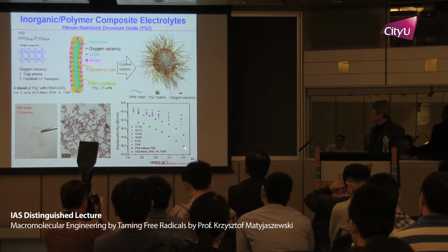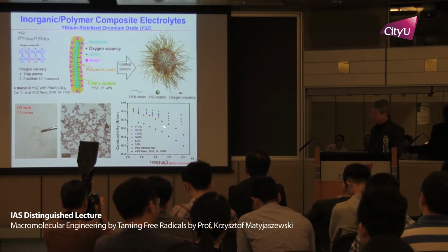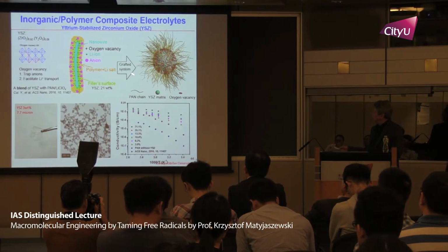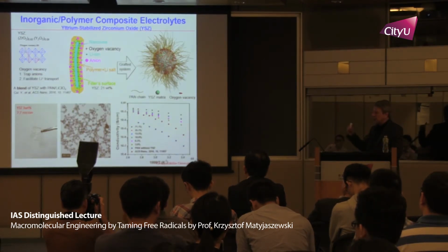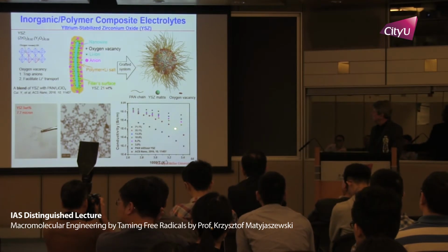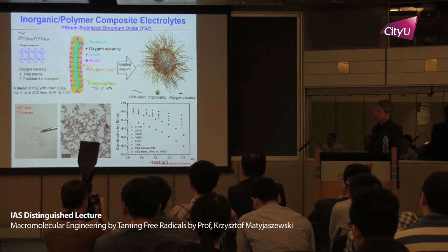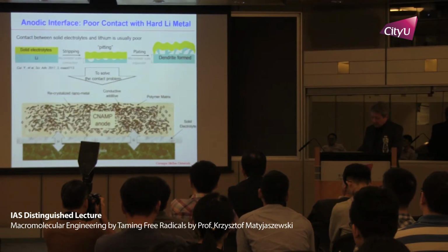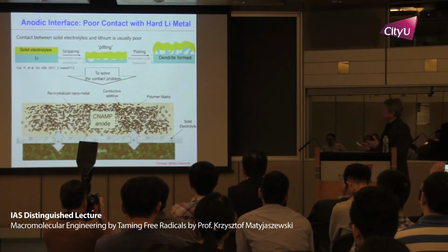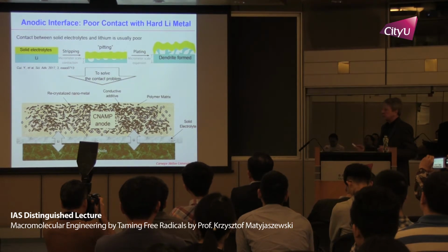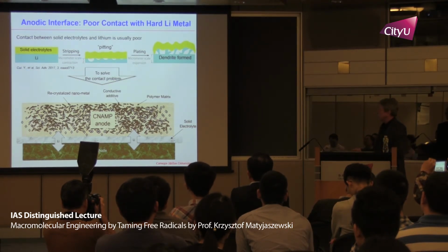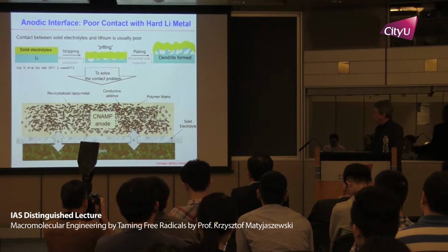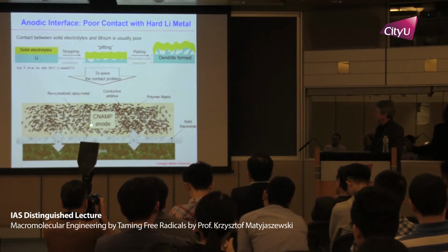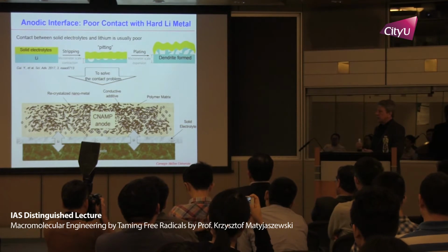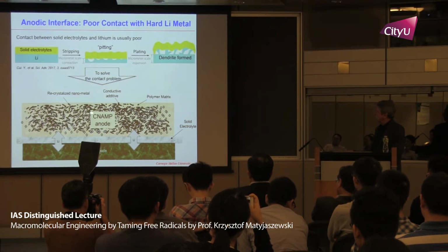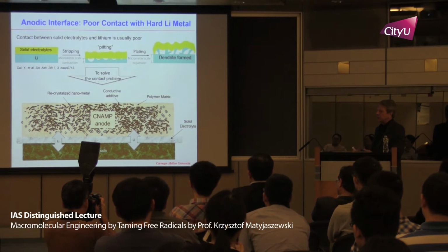So this is polyacrylonitrile alone. This is a mixed system, from this paper. And now if you graft from this YSZ polyacrylonitrile, you could see that conductivity is increased by more than one order of magnitude. So the idea which we had was really that if we want to prevent this dendrite formation, can we, instead of a liquid electrolyte, have a solid electrolyte, and then this anode can be really composite materials based on the nanoscopic alkali metal particles.